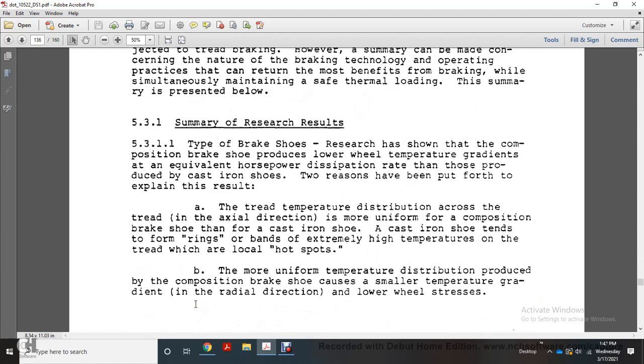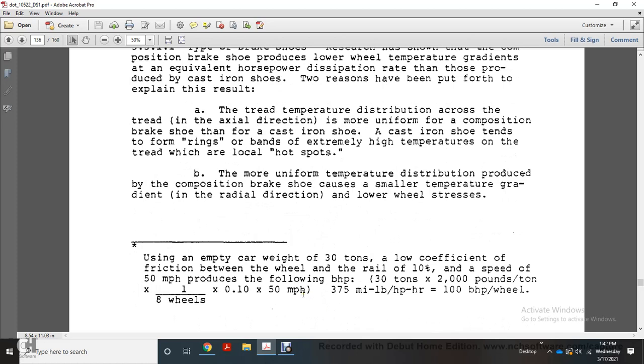Some of the research on brake shoes showed that the composition brake shoe produced a lower wheel temperature gradient than the equivalent horsepower dissipation rate with a cast iron shoe. Two reasons have been put forward to explain these results. The tread temperature distribution across the tread varies, with a more uniform distribution for the composition brake shoe. The cast iron shoe tends to form rings and bands of extremely high temperature on the tread, which are local hot spots. The more uniform temperature distribution produced with the composition brake shoe causes a smaller temperature gradient in the radial direction, and lower wheel stresses.